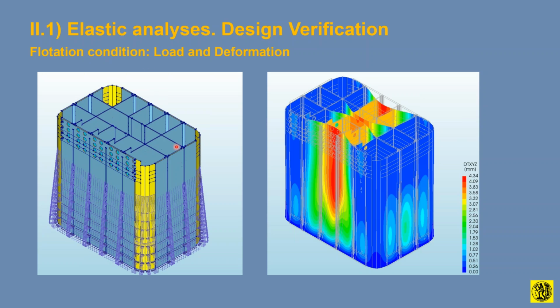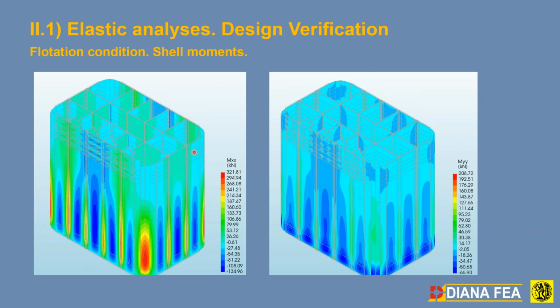This is a load case using Diana. Of course, in the elastic analysis, the steel is inactive, but we left it in, it doesn't make any difference. Still, the concrete was C30. In fact, we use the total strain crack model, which is supplied by the model, but in a linear elastic analysis, it's using the material properties as a linear elastic solution. So if we look at the deformations of the flotation case, using the full 3D model, we can see that there is, of course, the flexibility of the inner chamber here during the flotation causes a 4.3 millimeter cave-in of the perimeters under the flotation sea conditions.